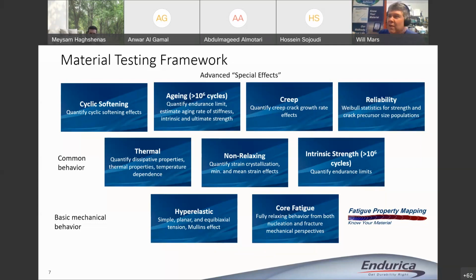I know people who do metal fatigue always think that if you increase mean stresses, that's bad. For rubber, that's not always true. Sometimes it's like that, but if you've got crystallization, there are conditions where you can benefit from this. And so if that's the case, then you would need to characterize that. We measure, in cases where we have very long fatigue life, it becomes important to know what that fatigue limit is. We can also look at cyclic softening, which is when you cycle rubber, the stress strain curve gets softer and softer gradually over time.